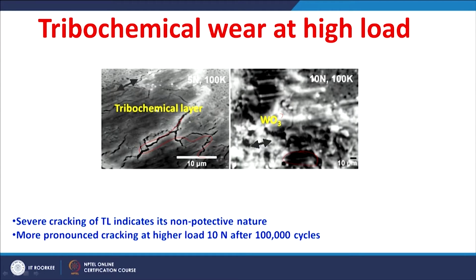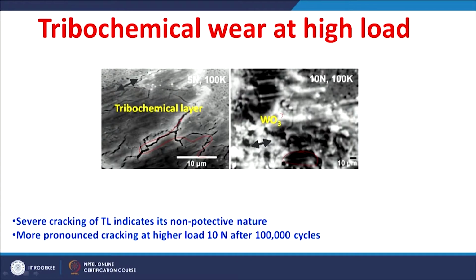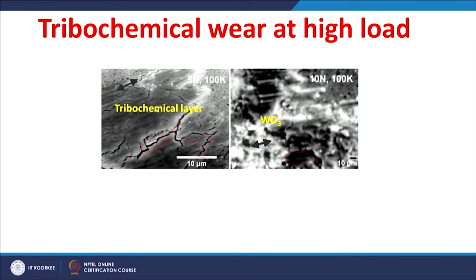So, when the tribo layer is non-protective, it cracks, and then the underneath surface is again subjected to further wear. So, at a higher load of 10 Newton, more pronounced cracking is observed after these 100,000 cycles. So, tribochemical wear is dominant at higher loads, that is 5 Newton or more. At lower loads it is mild abrasion, and at higher loads of 5 Newton or more it is tribochemical layer formation and then removal, that we call tribochemical wear. So, there is a change from abrasion to tribochemical wear with change in the load in these studies.